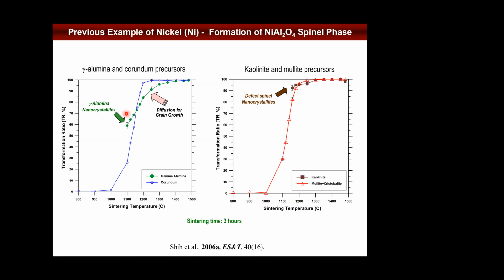And in order to know the quantity, you can really tell: when you are at lower temperature, if your processing technique is only capable at lower temperature, then you should choose gamma alumina for high efficiency of capturing and transforming heavy metal like nickel. But when you have a higher temperature capability, then you'd rather use alpha alumina.